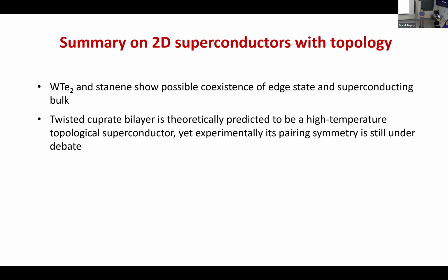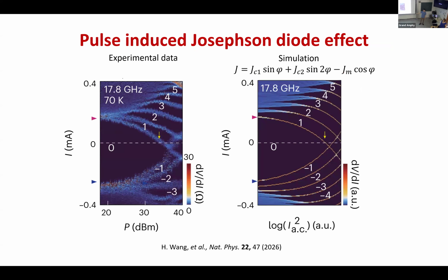So that you have still something that remains shows that there is apparently enough coupling for the second harmonic, if it is nominally tunneling. But not necessarily second harmonic, because we believe the first order tunneling is still there, which is not easy to understand if we just think about purely d-wave. We are trying to say there is an s-wave, which is more straightforward. Then nobody likes it.